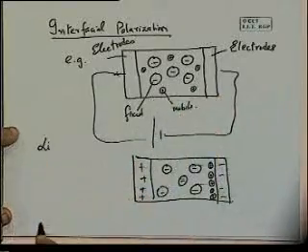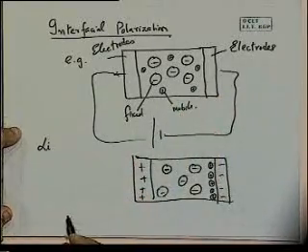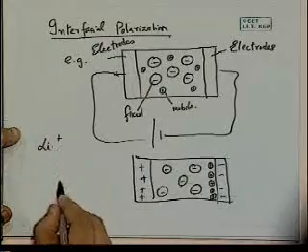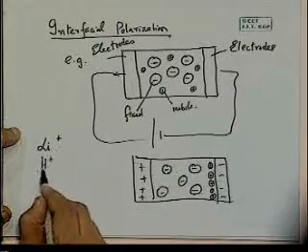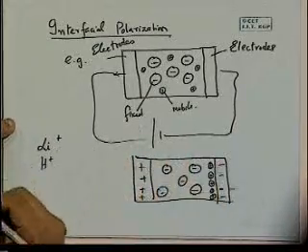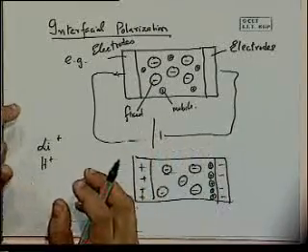I just mentioned this kind of mechanism, but I didn't give you an example. For example, lithium is one example, being a very small positive charge, or hydrogen, that can migrate through a dielectric like this. These are some specific examples. They are put to good use actually in practical situations, but their very size means that they are able to migrate, whereas the bulk of it, the negative charge, remains fixed in its place.